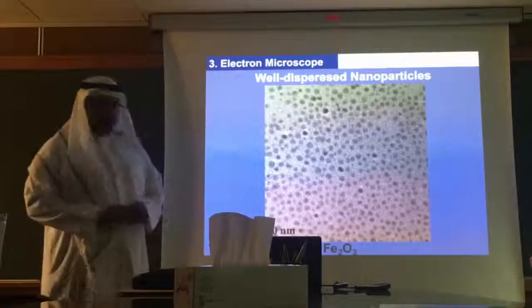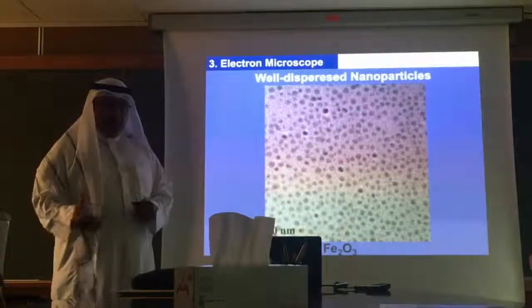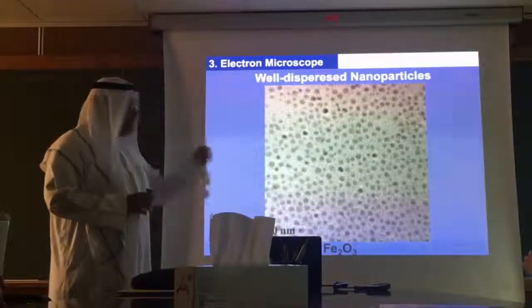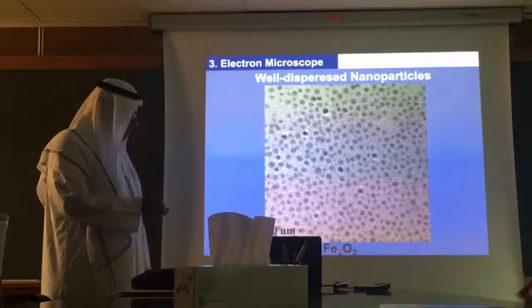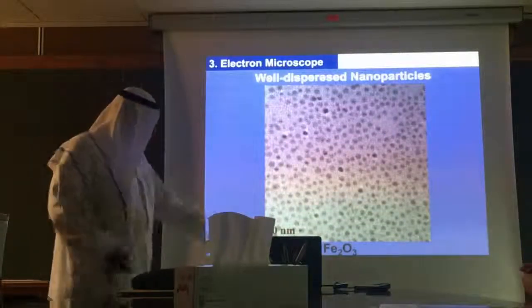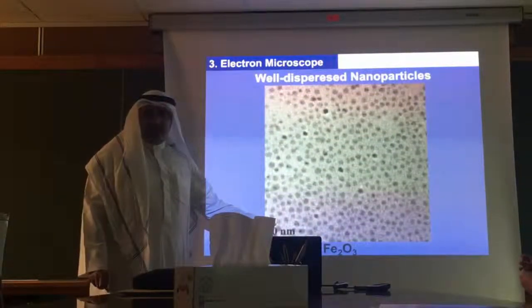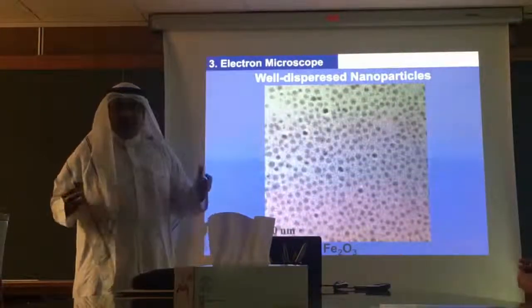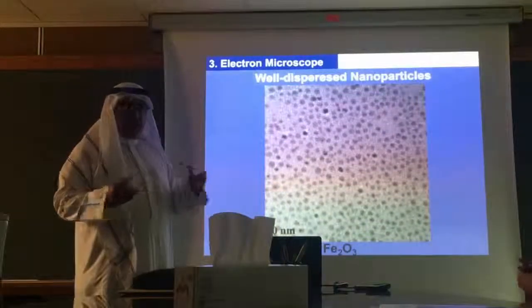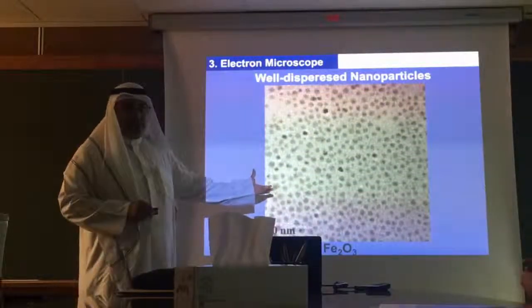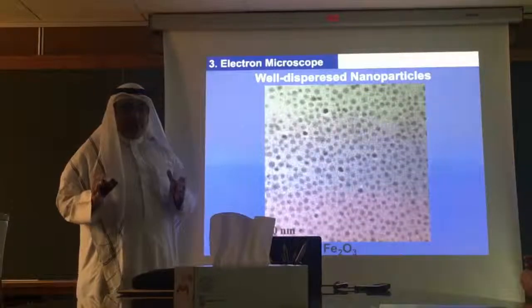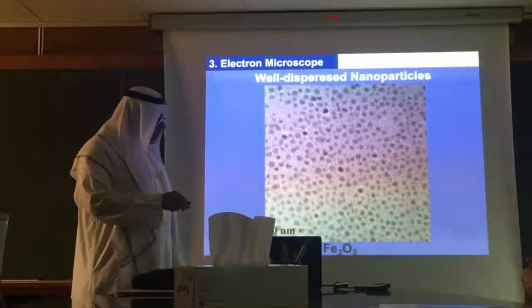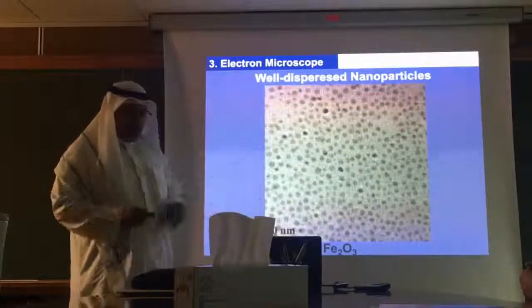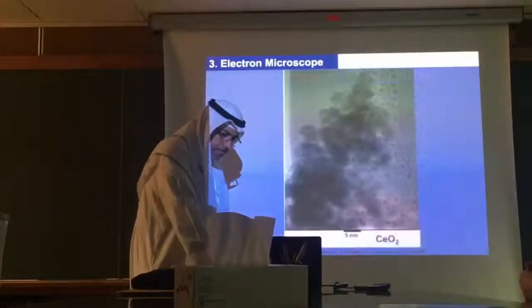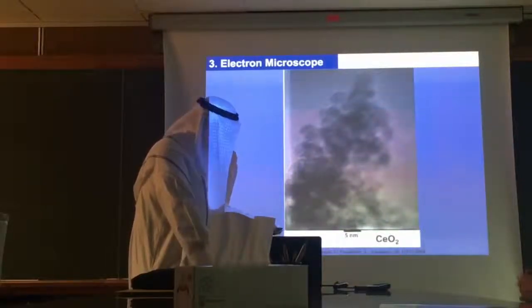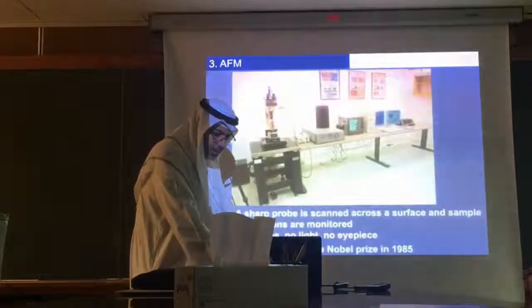Okay, these are the nanoparticles that I told you about. If you use the bottom-up approach with some sort of control, you can control the size of the nanoparticles. This material I prepared a long time ago, and we found out the particles are less than 5 nanometer. And you can see how homogeneous it is actually, how monodispersed it is. The particles are very, very similar in size, and we can disperse them very easily in a solution. So if I have an application that will benefit from iron oxide in a solution, this will be a very excellent example for it. This is another material that I did with cerium oxide nanoparticles.